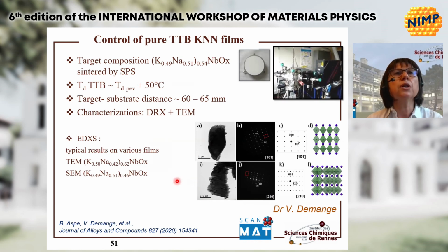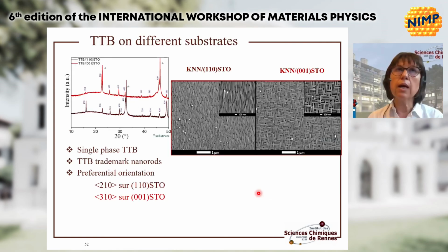Now, what about the results? Thin films have been deposited from a new target that has been prepared by SPS. The films have been analyzed by EDX in transmission electron microscopy, but also by scanning electron microscopy, and we can observe a composition near the expected one for the TTB phase. The transmission electron microscopy and X-ray diffraction patterns have shown that we have a pure TTB phase, here in the case of films deposited on strontium titanate with 2 different orientations with an epitaxial growth. And you can see here the trademark microstructure of the TTB phase with elongated grains and in some cases nanorods.